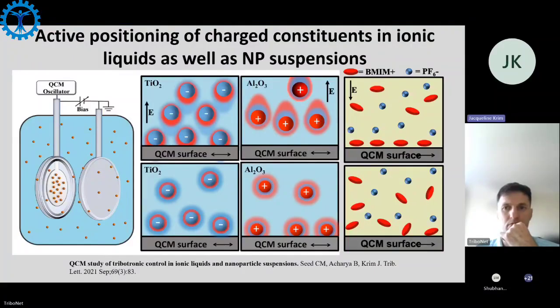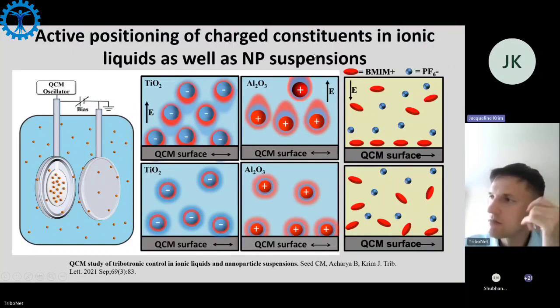This is showing one result that we do want to comment on. You never really know if the friction will go up or down when we deposit alumina on the surface. By adding the nanoparticles, the friction went up. On some of the ionic liquids, if you get this layer deposited on the surface, the friction actually goes down. So again, it's a matter of screening required. Next slide.